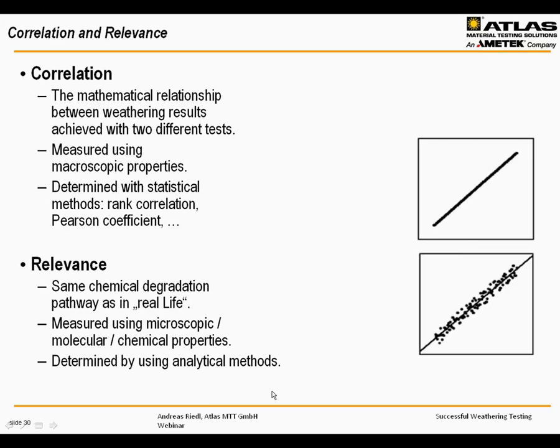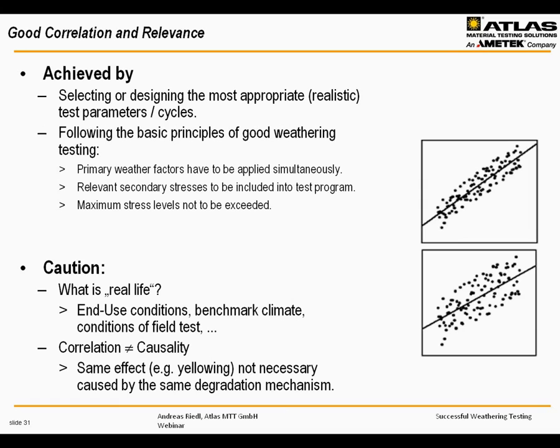Relevance is usually determined by using analytical methods, spectroscopical methods, chemiluminescence, microtoming also, all kinds of analytical methods are used here to find out if there's any distortion in the chemical degradation. It is important to look at both. A good correlation and relevance is achieved by selecting or designing the most realistic test parameters and cycles and following the basic principles of good weathering testing, which means the primary weather factors have to be applied simultaneously as it happens in reality, as we saw before. The relevant secondary stresses should be included and the maximum stress levels should not be exceeded.